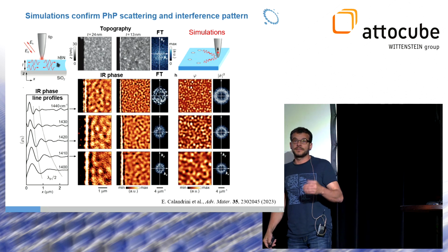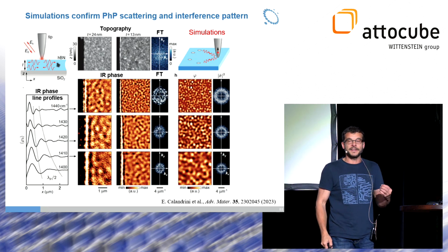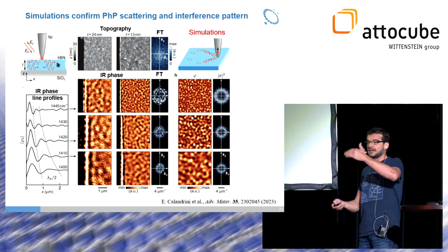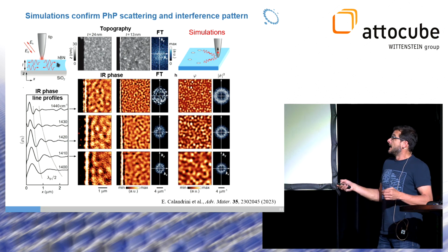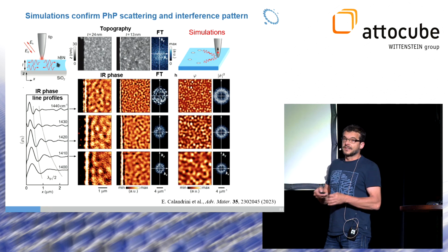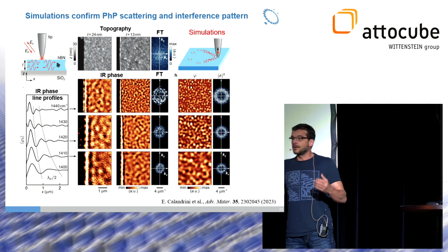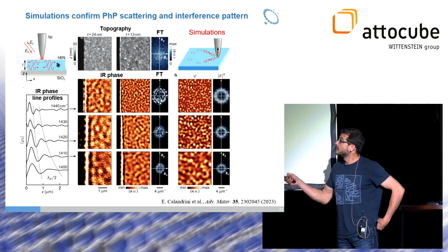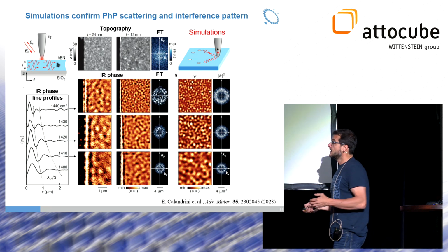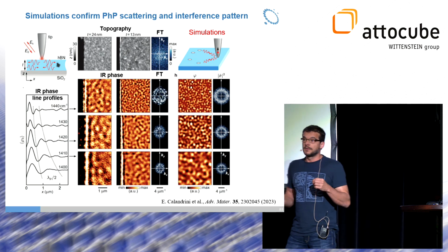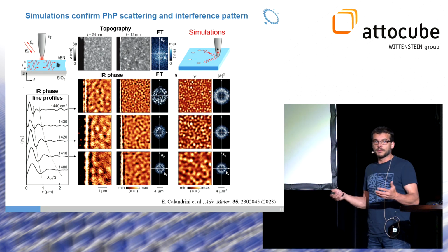So that means we have a CVD-grown hBN that we can stack. We can make that even 50 nanometer thick. We have phonon-polaritons. All is nice. But of course, if you're, let's say, interested in guiding light or making fancy optics, it's probably not very useful because these polaritons, they scatter everywhere. So is that useful? Not for these types of applications, but we are anyway interested eventually in ribbons and resonators.